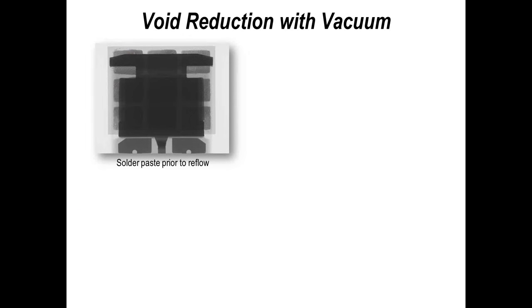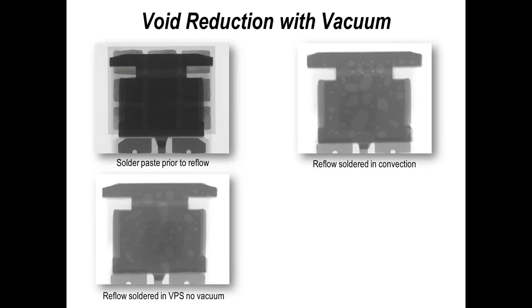So here's a couple of examples that I've included in this presentation. First of all, this is an example of a large transistor package sitting on the solder paste prior to reflow. So you can see the solder paste, you can see the package, and this is not untypical with the challenges that many of us as engineers have to face. The next two examples show reflow in convection and reflow in vapor phase. And arguably, there's not a lot of difference between them. You can see a fair amount of voiding present underneath both packages.